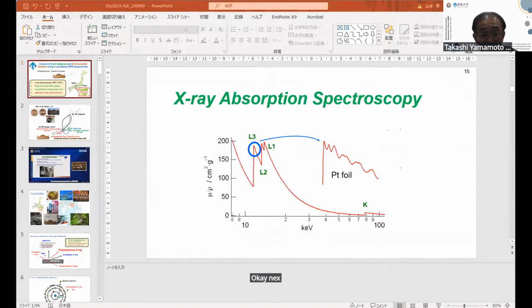Okay, next I'll talk about X-ray absorption spectroscopy. This is the absorption spectra of platinum recorded with high resolution spectrometers. You can see the K edge and the L1, L2, L3 edges. If the X-ray absorption spectra are recorded using high resolution spectrometers, small but fine structures can be seen like this. These fine structures contain useful information about the